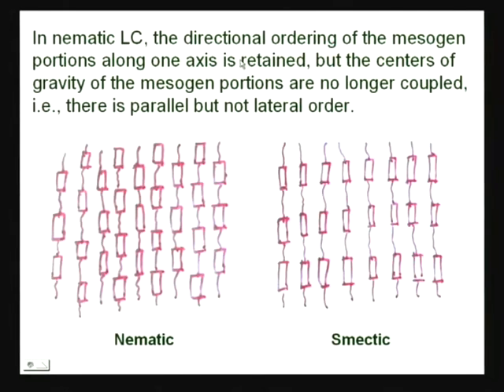In nematic LC, the directional ordering of the mesogen portions along one axis is retained, but the centers of gravity of the mesogen portions are no longer coupled. There is parallel, but not lateral order. Consider this one. This is nematic, this is Smectic. Look at these two models, nematic model and Smectic model. Here you see these are mesogens, which brings molecular order leading to liquid crystalline behavior. In this molecule mesogens are placed like this, in this molecule mesogens are placed like this.